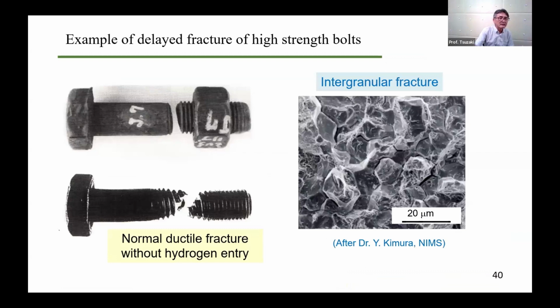As many of you gathered here today are aware, accidents of delayed fracture are significant and famous for high-strength bolts. In this case, intergranular fracture also occurs. And it has been discussed that hydrogen segregation at the grain boundary and reduced cohesion are one of the main causes of embrittlement.